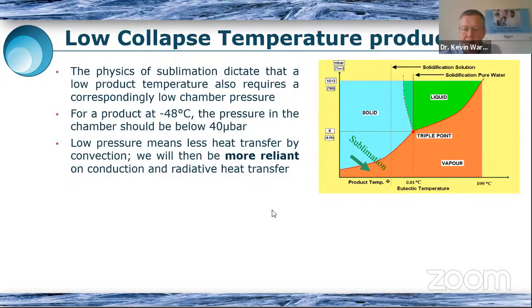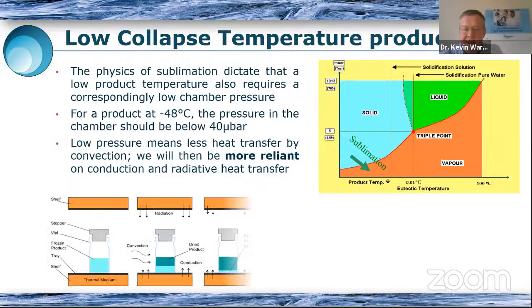But for most products, we need to go way lower in temperature, and so we have to go correspondingly lower in pressure. Now, one of the issues with that is that in freeze drying, we do rely on getting heat into the product to keep drying it. And we've got radiative heating, we've got direct conduction, but we've also got convection. And convection is also termed gaseous conduction. And as you can expect, gaseous conduction relies on there being a certain pressure in our freeze drying chamber in order to effect that heat transfer into the product. Otherwise, we're going to have extremely slow freeze drying.